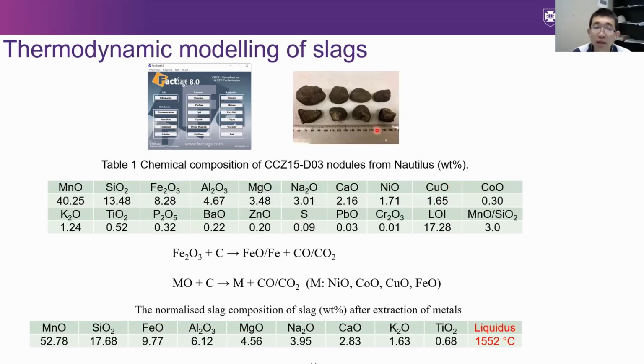So at the beginning, before we conduct the experiment, we use a commercial software, FactSage, to model the liquidus temperature. The liquidus temperature, actually the melting point, you can understand as the melting point of the slag that is operated at high temperature.